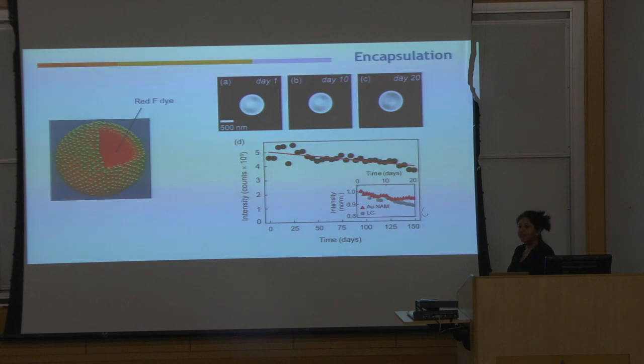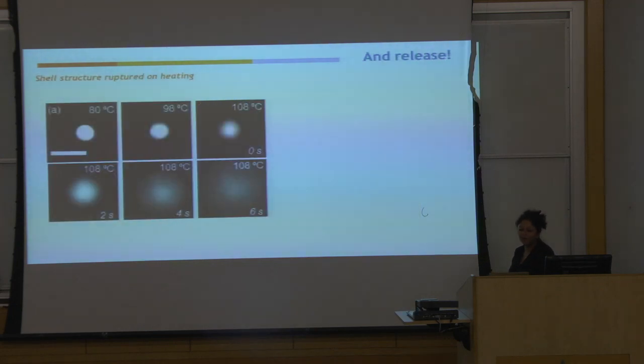After you put things in it, the fact that it can hold, then comes the question of how do we release this dye or the contents when we want it to. So the first thing is we heat up the shells. We are heating the shell here around 108 degrees Celsius. And this is heating just by putting it on a hot plate. And you're looking at the fluorescence of the dye inside. That's why we can see them. These shells are made out of gold nanoparticles, so they don't emit any light. It's starting to get fuzzy, which means the dye is starting to leak out. Within about 6 seconds at the same temperature, all the dye comes out. Presumably, the shell has broken.